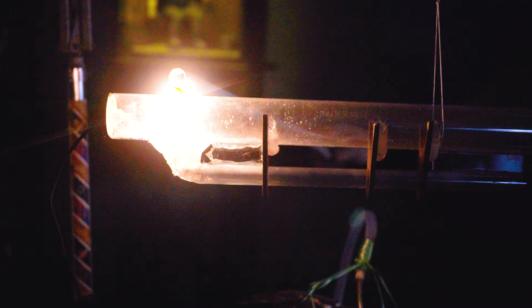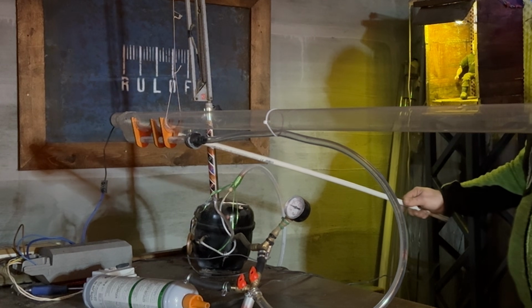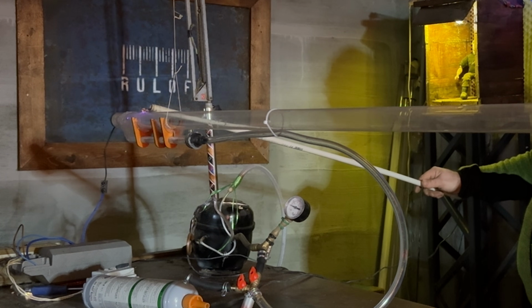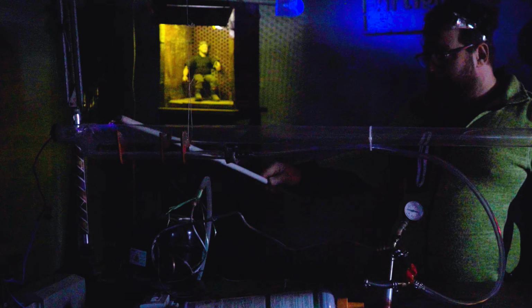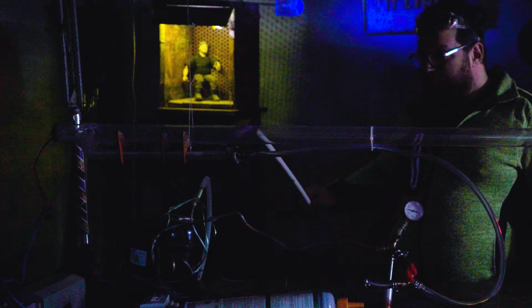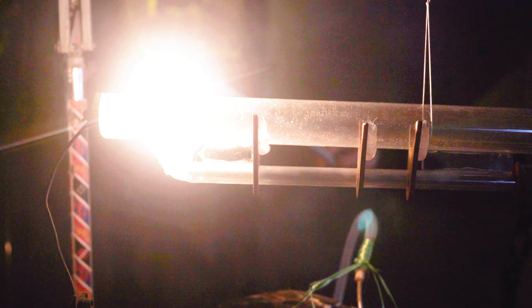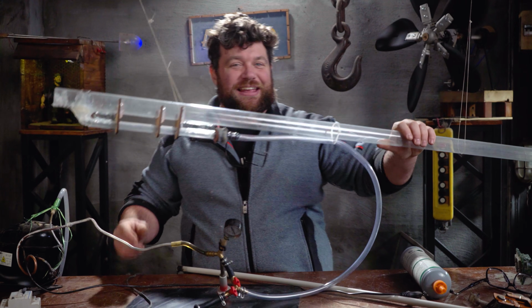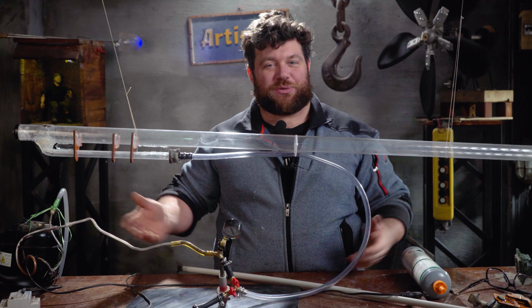And you can see that it's working. Unfortunately, the camera doesn't really catch how bright this plasma is. You can see that we are melting the silicone and the epoxy that is outside, but overall the plasma is still visible inside, so this is so promising. I'm so happy. And consider that this is completely homemade from scrap pieces.